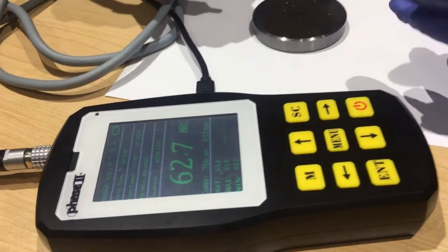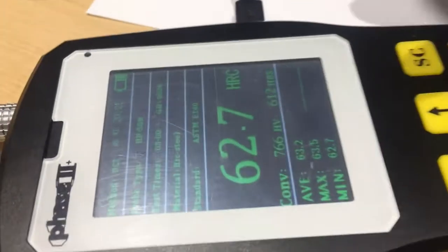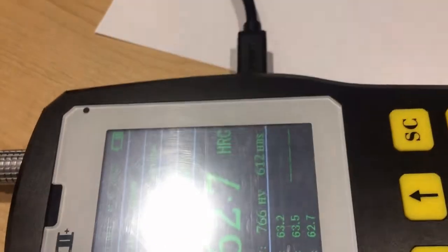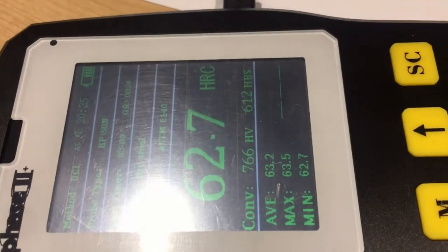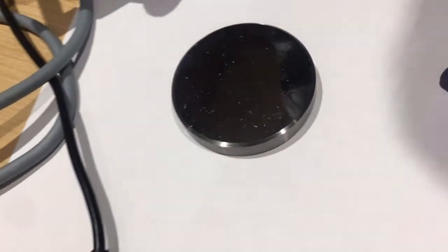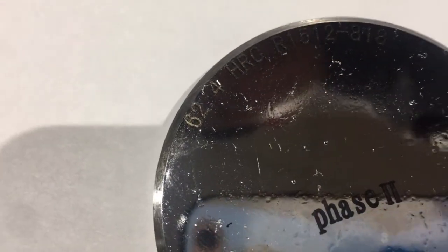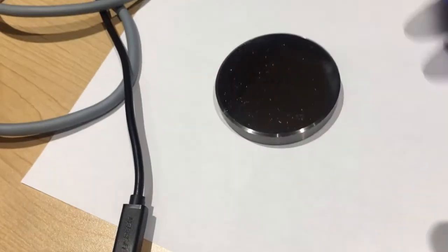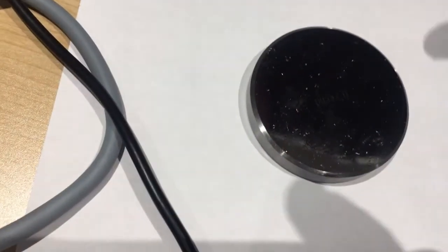Now on the machine, we can see the max and min and average here. The average is 63.2, which is 0.8, a little bit higher than the block's standard hardness. That's an acceptable result. And here, as you use the block, it leaves something on it, but don't worry about it. It's big enough for you to test.